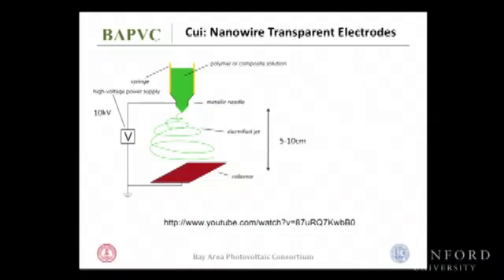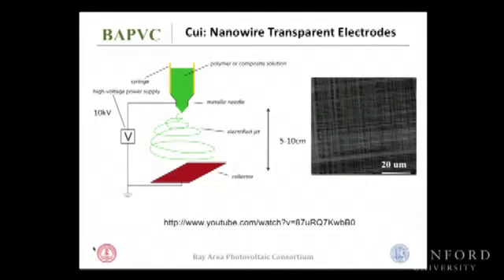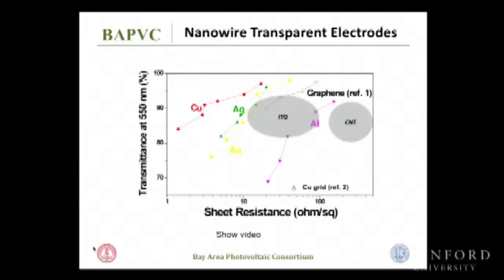So this type of process allows us to make a nanowire mesh like this, of metallic wire like copper. And based on this idea, extending to more metals, now you are really seeing great performance. This is transmittance versus sheet resistance. For copper nanofiber, you get more than 90% transmittance with only a few ohms per square. Really, really great performance.